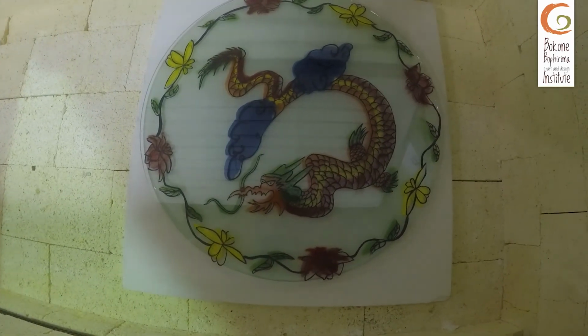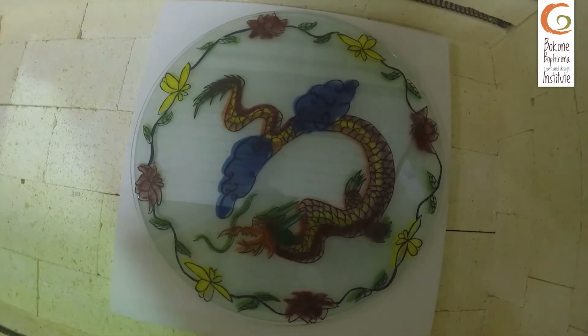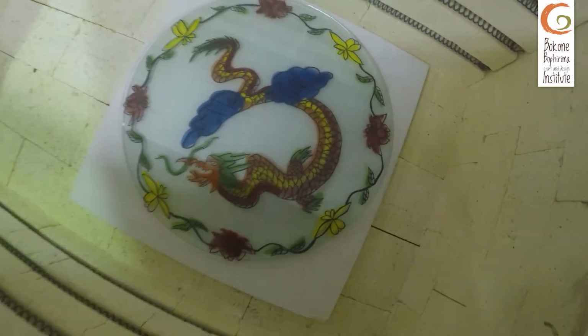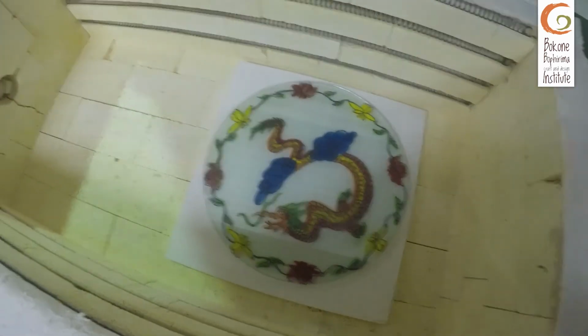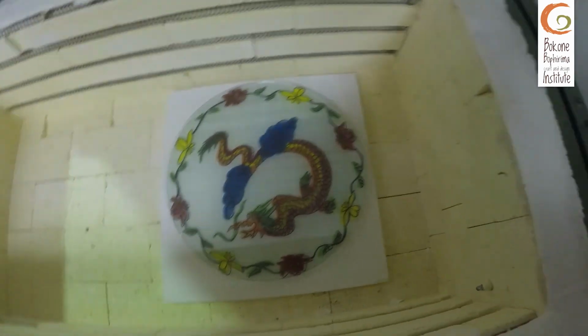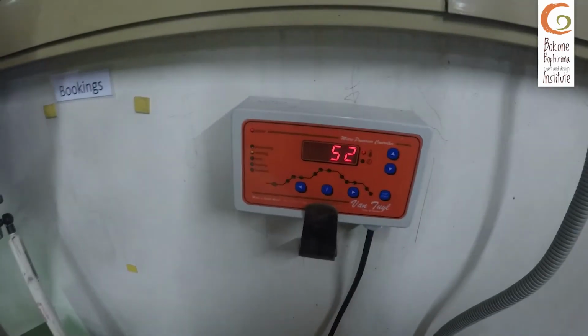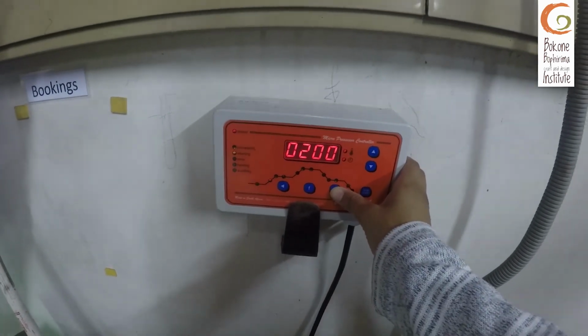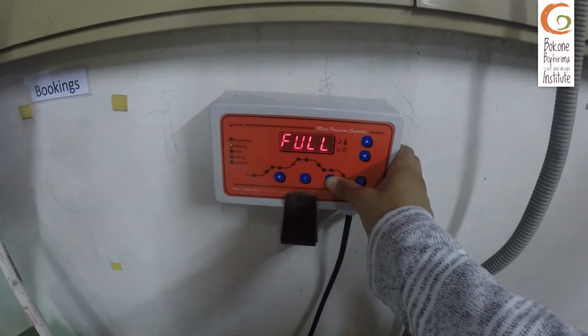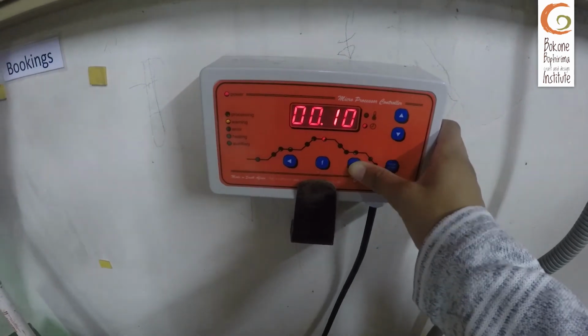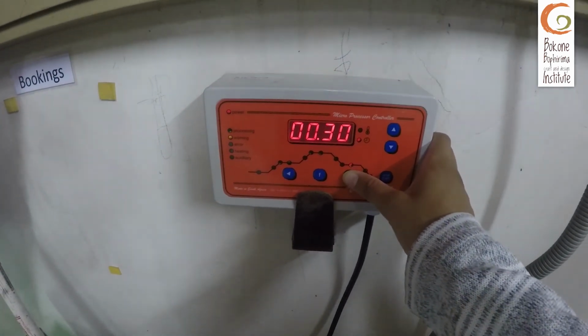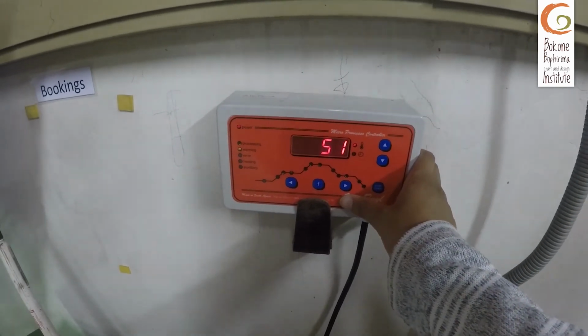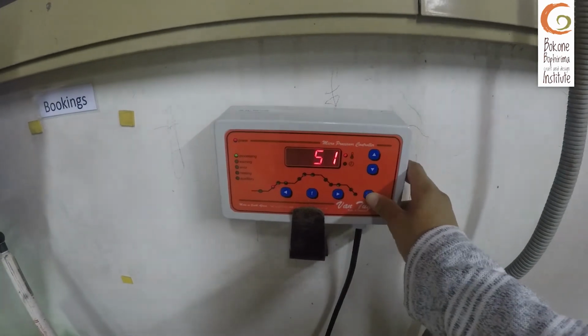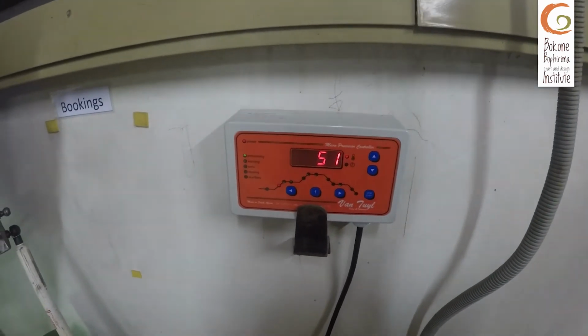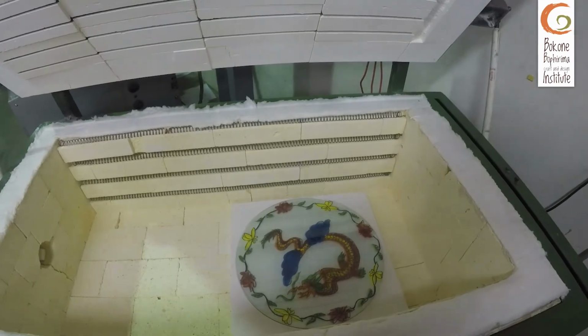We now come to our kiln program. Our kiln is reading 52 degrees Celsius. We are starting immediately, and we're going up the ramp at 200 degrees to 680, soaking for 30 minutes. Going full up to 850 degrees, soaking for 10 minutes, coming full down to 580 degrees, soaking for 30 minutes, coming down at 100 degrees to 30 degrees, and we can start our program immediately. We close our kiln door halfway, and once it reaches 100 degrees, we close our kiln completely.